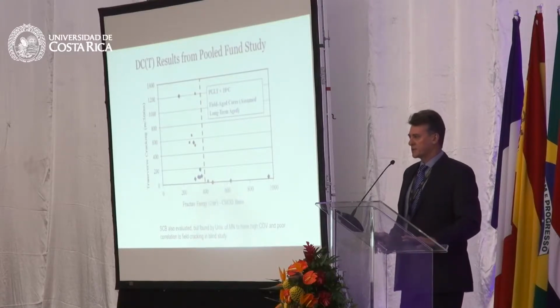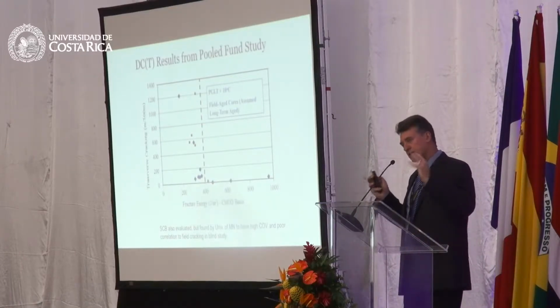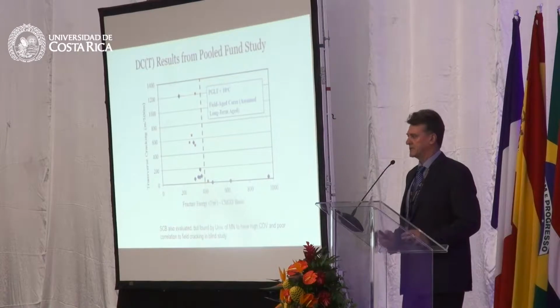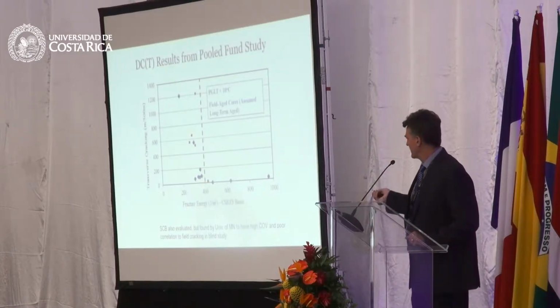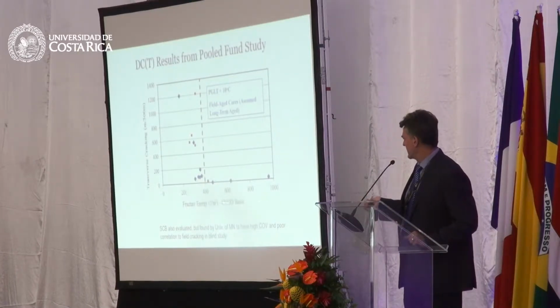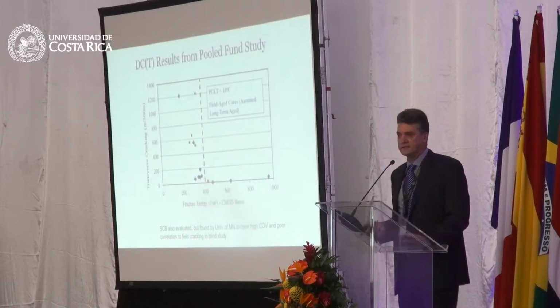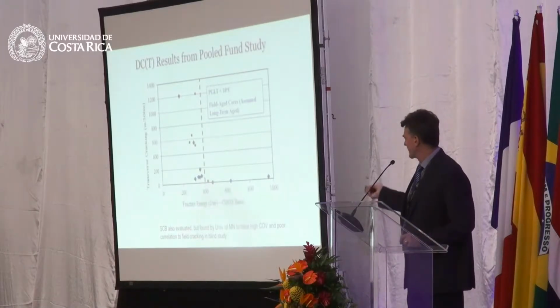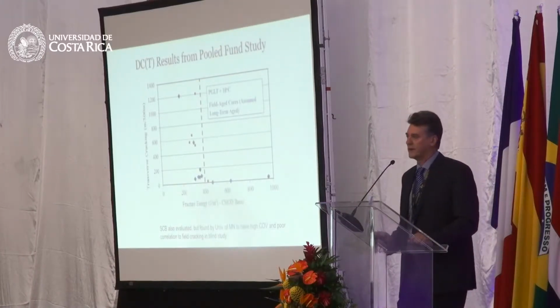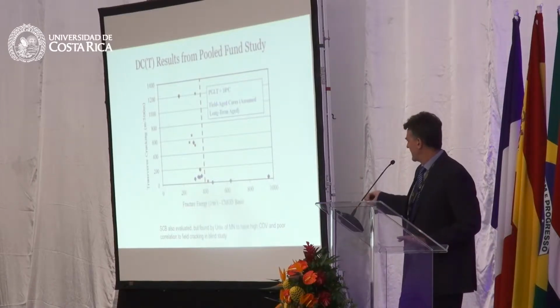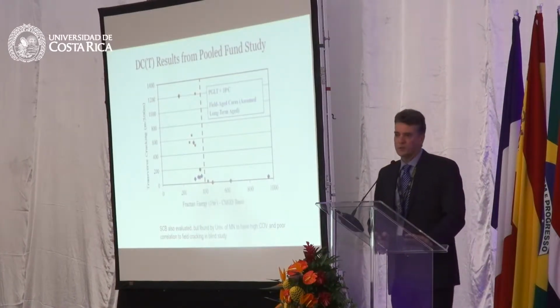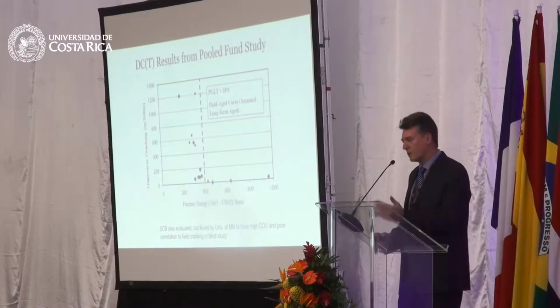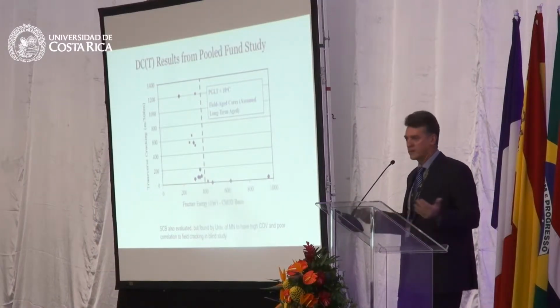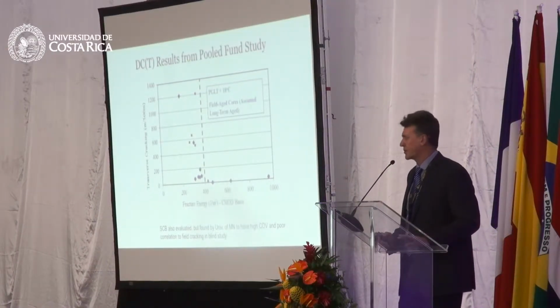We had a rather large study involving multiple states in the United States where we correlated the fracture energy we get from the DCT test with transverse or thermal cracking. We found a threshold value of around 400 joules per meter squared, and mixtures above that value, we really didn't notice much thermal cracking in the field.